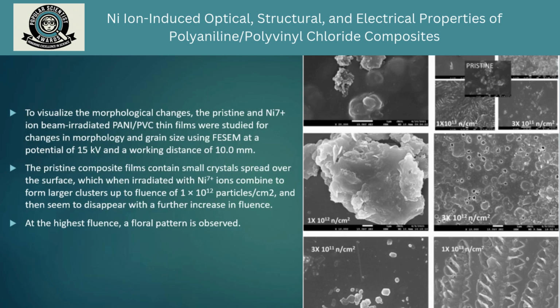FESEM has been conducted to visualize the morphological changes in the pristine and nickel 7+ ion beam irradiated PANI-PVC thin films, and the changes in the morphology and grain size have been observed at a potential of 15 kV and at a working distance of 10 mm. The pristine composite films contain small crystals spreading over the surface, which when irradiated with the nickel 7+ ion beam combine to form larger clusters up to a fluence of 1 into 10 power 12 particles per centimeter square, and then seem to disappear with further increase in fluence. At the highest fluence, a floral pattern has been observed.